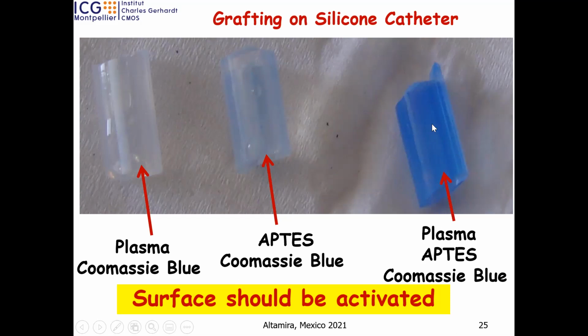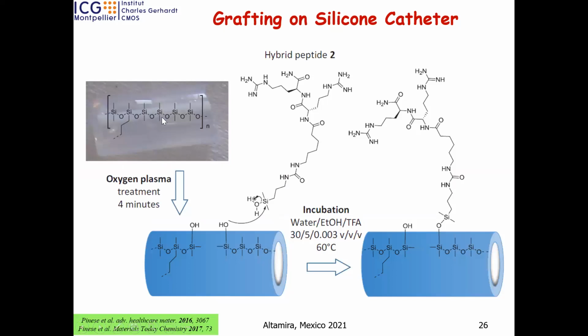You can see clearly it's very blue, that you have a lot of amino groups on the surface if you activate your surface just before. So for this reason, we demonstrated that all surfaces should be activated by plasma before coating. So, how do we explain the activation? You have your silicone catheter here. After activation for 4 or 5 minutes, you break some bonds here.